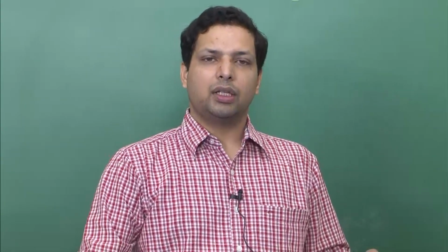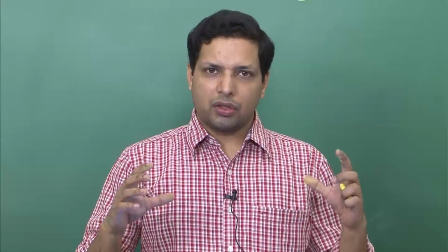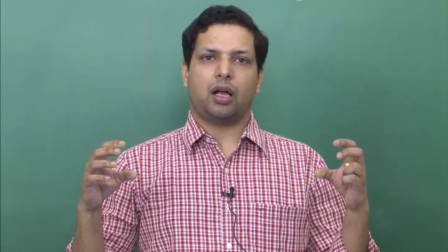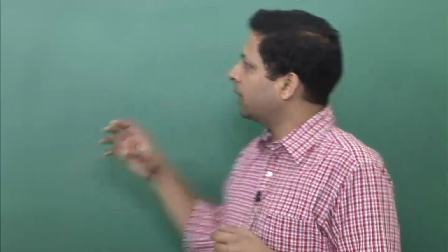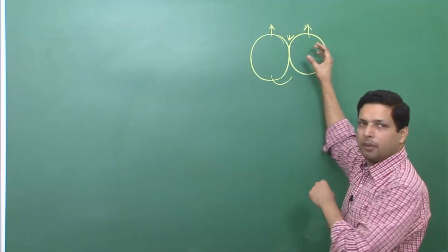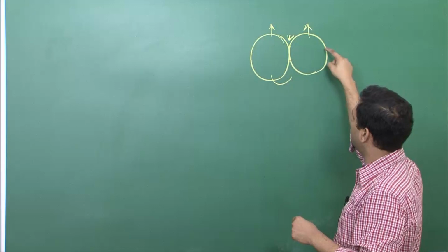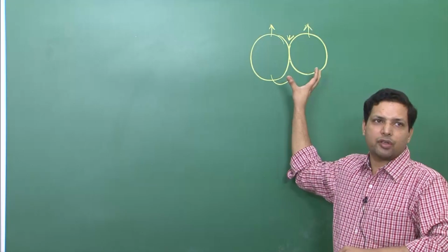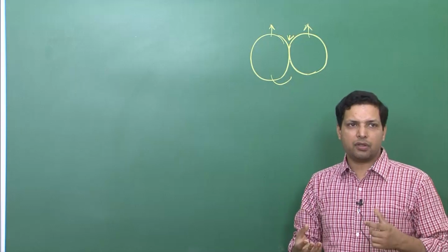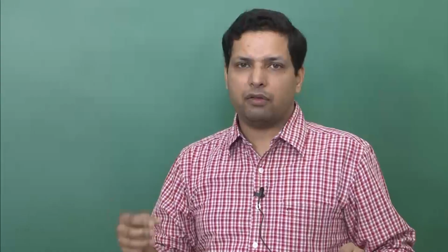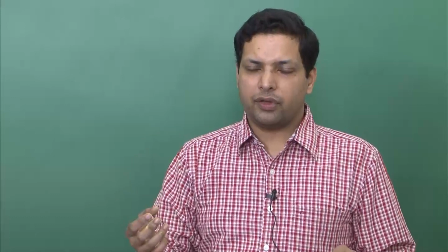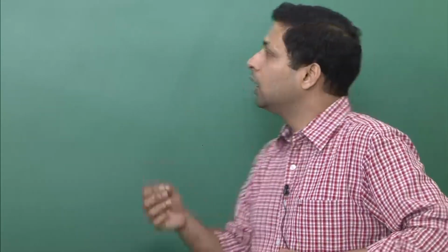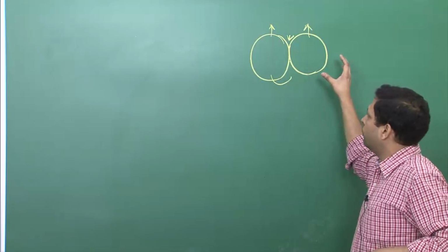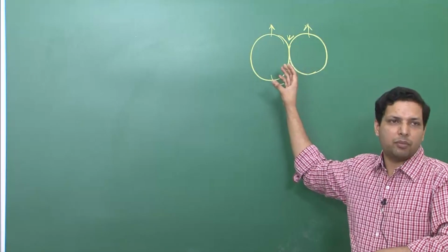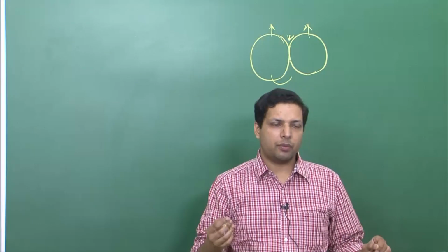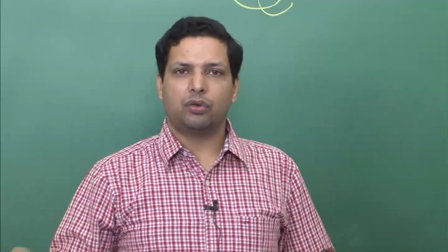Then there is plastic flow. Again, surface tension can cause compressive stresses. So, there are again these two particles you see over here, and because of the diameter that exists over here and over here, there may be compressive stresses generated. Whenever there are compressive stresses generated, you can imagine there will be some deformation, only if the stresses are very high, of course, but let us say the stresses are high enough. Then it can cause plastic deformation at some level, and that plastic deformation will cause plastic flow of the material to, again, the neck region.